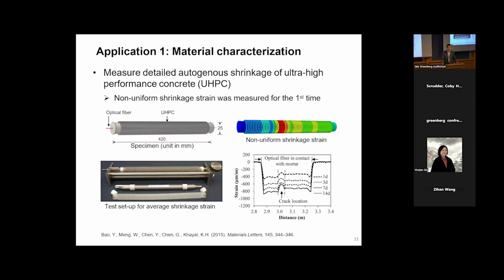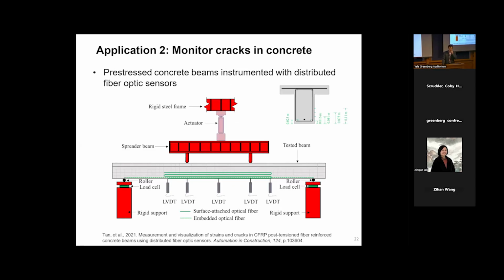Then how can we use this in materials research? As I mentioned, my collaborator is a materials expert, working mainly on concrete or cement-based materials. According to ASTM's test standard, we assume the concrete material has uniform shrinkage because of, for example, the water loss during the reaction. There's a volume change. We assume this volume change is uniform, but according to our measurements, we found that it's actually not uniform. Therefore, it's important to characterize this non-uniform shrinkage strain, so that we can better characterize the materials.